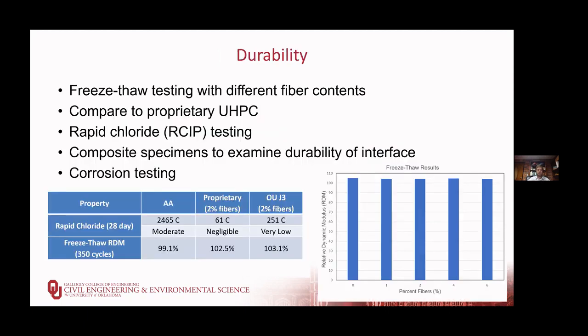For durability, we looked at freeze thaw testing of the UHPC material itself with different steel fiber contents. And we can see on the bottom right that we basically had no deterioration out to 350 cycles of freezing and thawing with any fiber content that we examined. We compared it to a proprietary UHPC and found, again, for 2% steel fibers, so our base case, very similar performance. For rapid chloride ion permeability testing, we found negligible and very low for the proprietary and non-proprietary UHPCs, respectively.